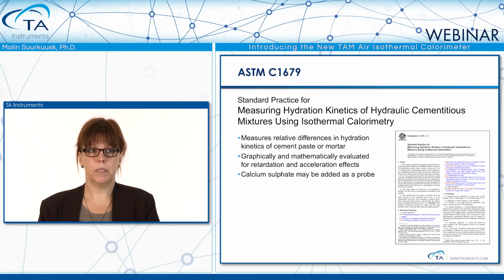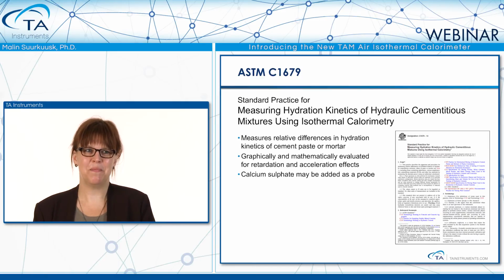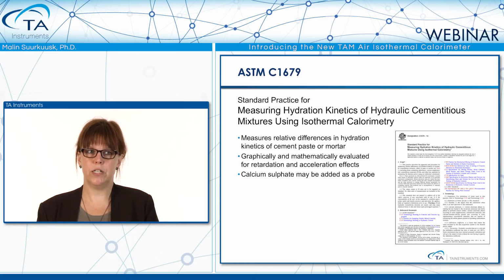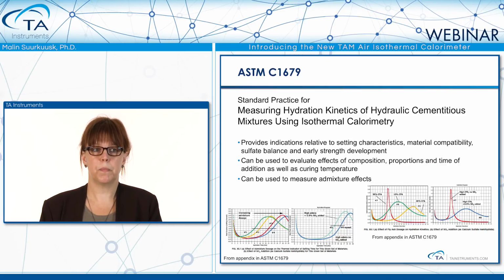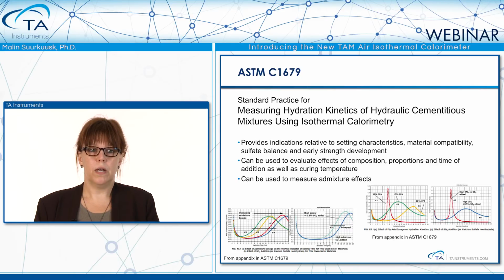Then there is the second ASTM standard, 1679, which is a standard practice for the measuring hydration kinetics of hydraulic cementitious mixtures using isothermal calorimetry. It will measure the relative differences in the hydration kinetics of a cement paste or mortar. The data is graphically and mathematically evaluated for retardation and acceleration effects. It's also stated that calcium sulfate may be added as a probe to see that there is enough sulfate to start with in the cement. And there we have some examples from the method itself, how it's graphically produced to see that the hydration profiles are different.